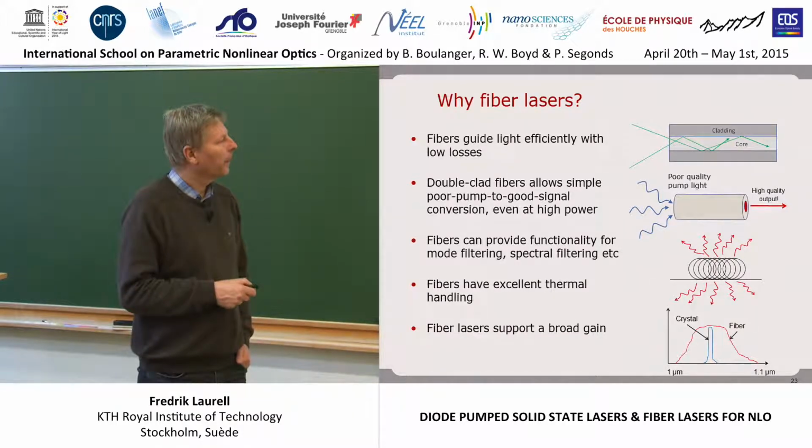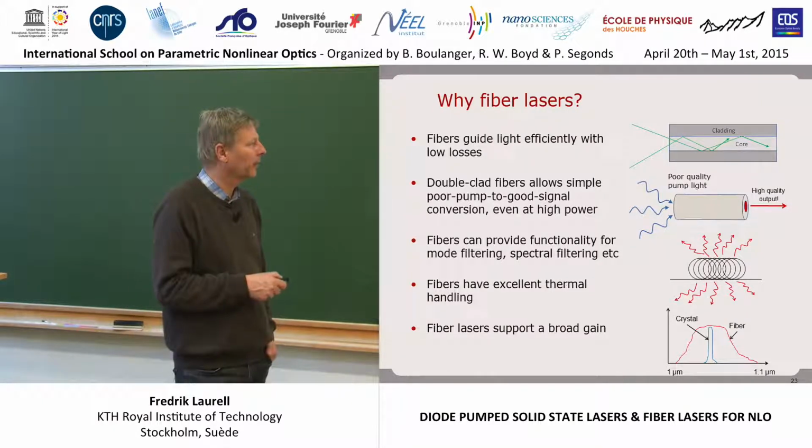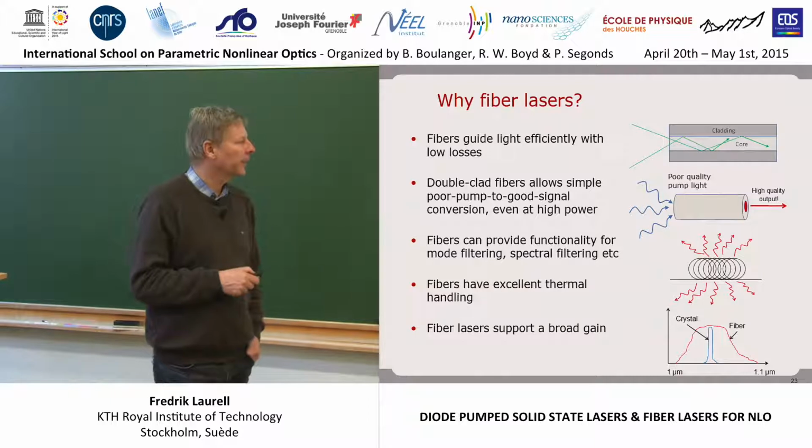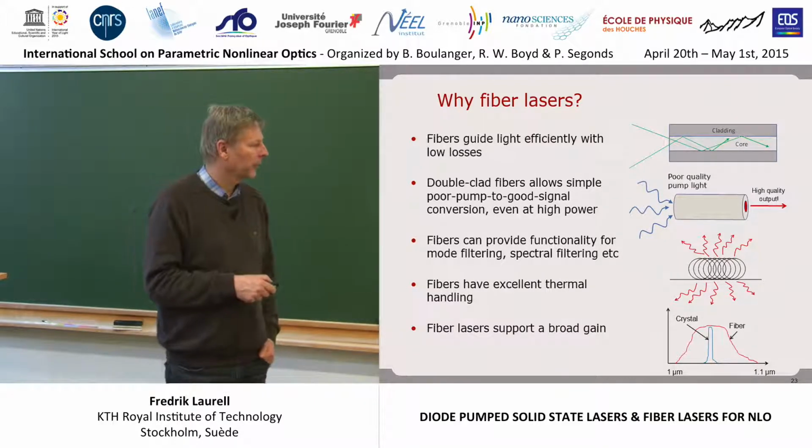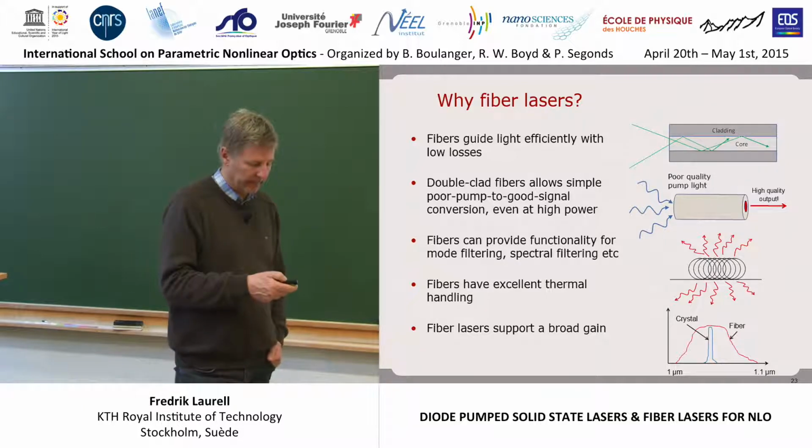And the pump light can be launched in the cladding, in so-called double-clad fibers. So it's easy to get a lot of energy in here, and it takes some time before most of it has been absorbed in the core. And then we can cool it. This is in a glass, so we have a broad emission spectrum. So they can be used for ultra-short pulses, or we can do tunable devices.